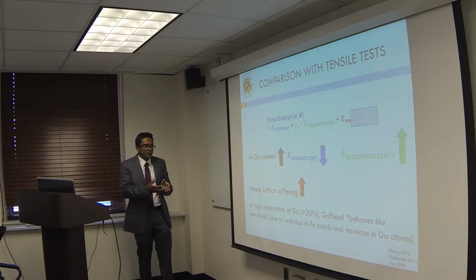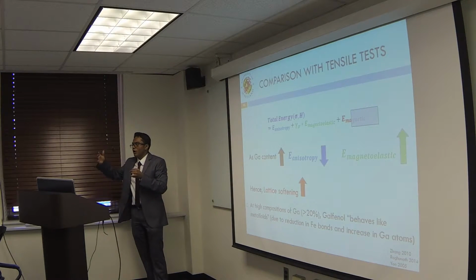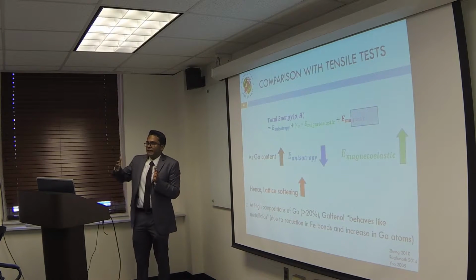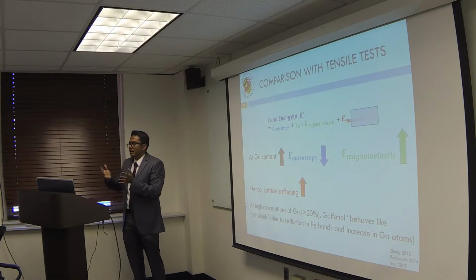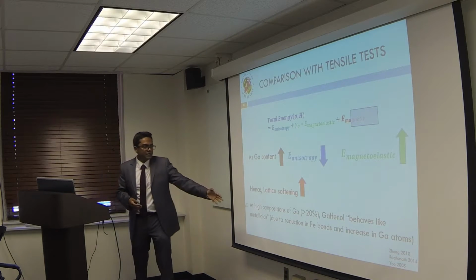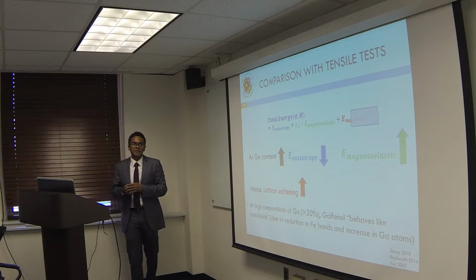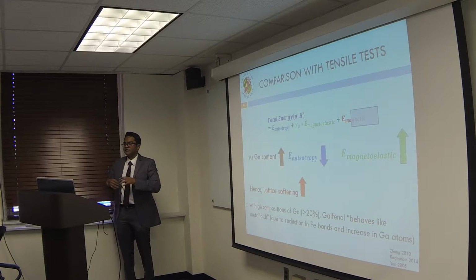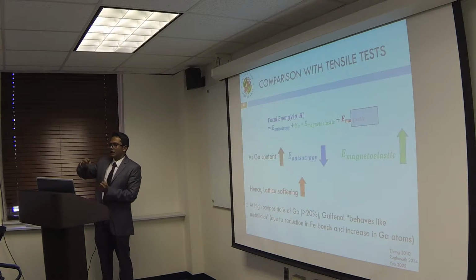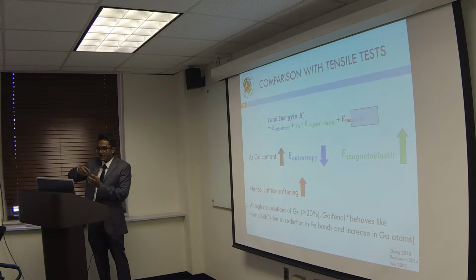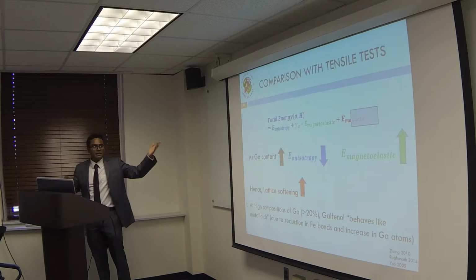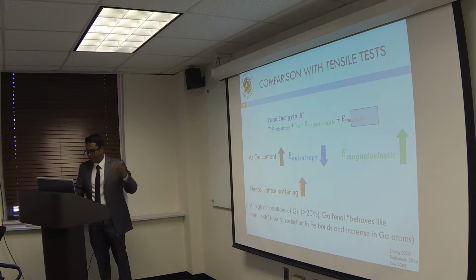And from a metallurgical perspective, as we keep adding more and more gallium in the alloy, it starts behaving more like a mixture of metals or a metalloid instead of an alloy. And this leads to a reduction in the number of iron bonds, and this leads to lattice softening as well. So as the gallium content keeps increasing, it gets easier for me to pull, and that leads to higher values of negative Poisson's ratio.